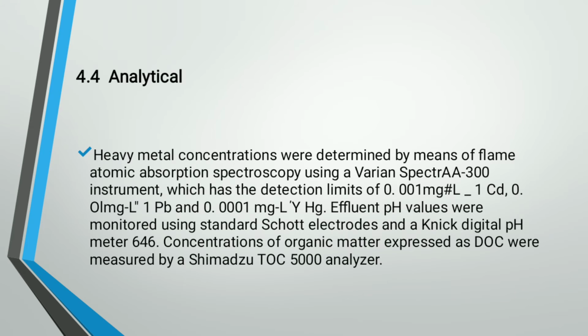Heavy metal concentrations were determined by means of flame atomic absorption spectroscopy using a Varian SpectrAA instrument, which has detection limits of 0.001 milligrams per liter for cadmium, 0.01 milligrams per liter for lead, and 0.0001 milligrams per liter for mercury. Effluent pH values were monitored using standard Schott electrodes and a Knick digital pH meter 646. Concentrations of organic matter expressed as DOC were measured by a Shimadzu TOC 5000 analyzer.